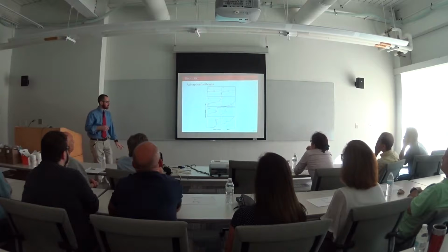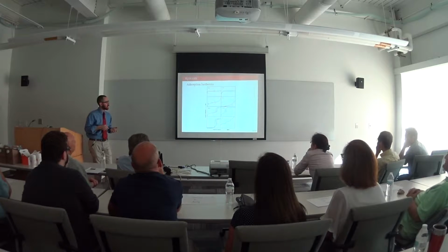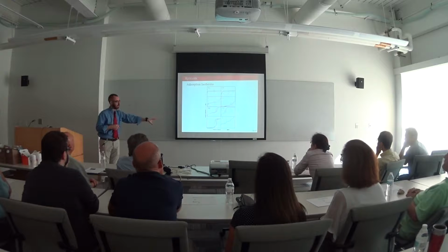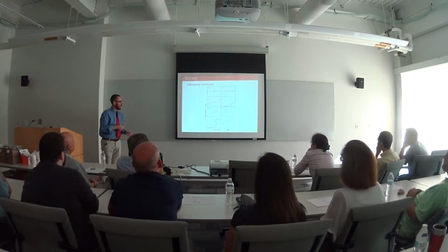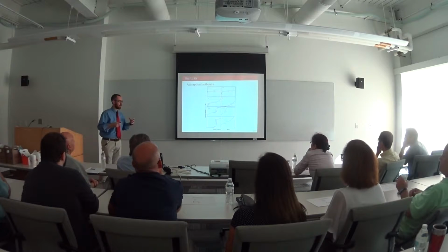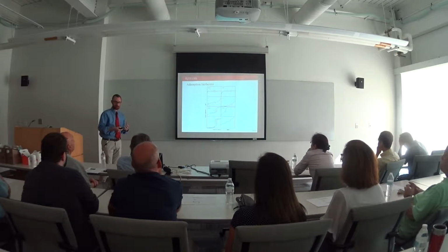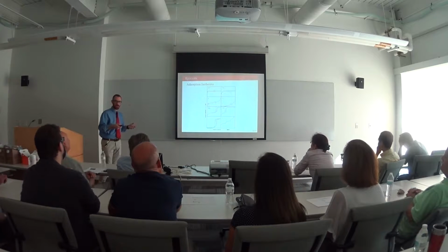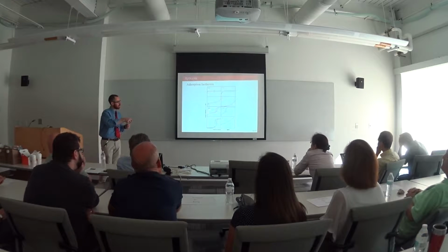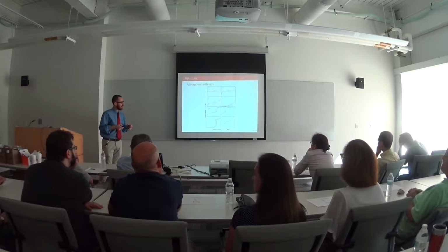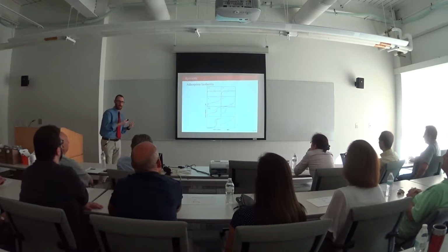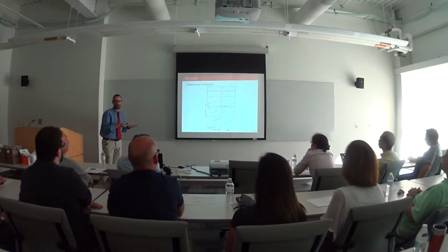So one of the main ways that we quantify adsorption is through something called an adsorption isotherm. An adsorption isotherm, and these are several different types shown here, is a graph of the amount adsorbed as a function of often relative pressure. So this is basically the uptake of your adsorptive at a certain pressure. And we do this over a wide relative pressure range to get our full adsorption isotherm. And adsorption isotherms can have very different shapes based on all the characteristics of your material, and this is where we derive all that useful information from.